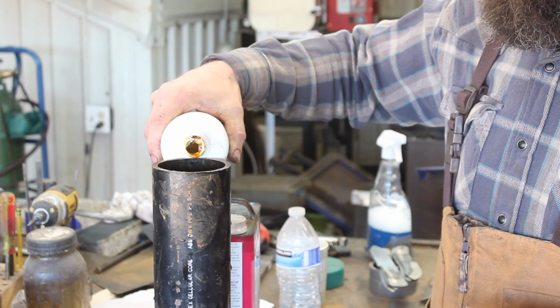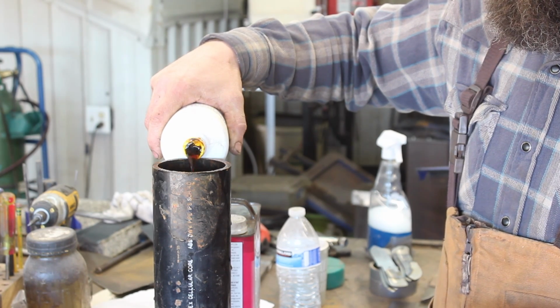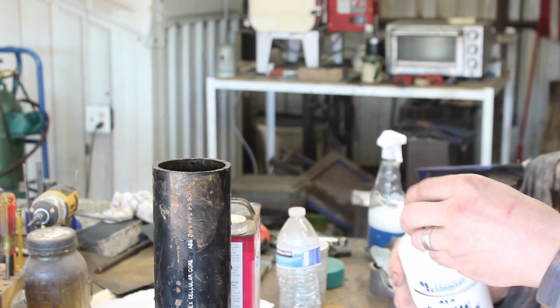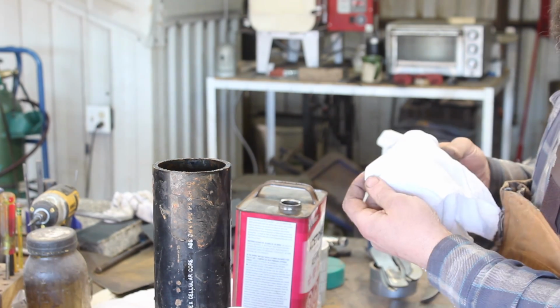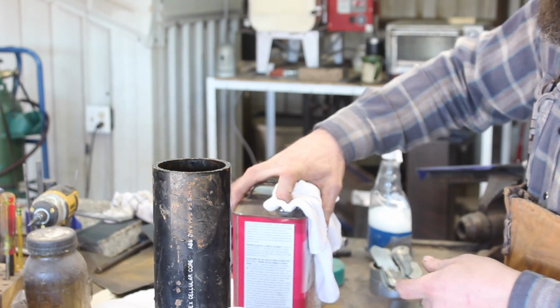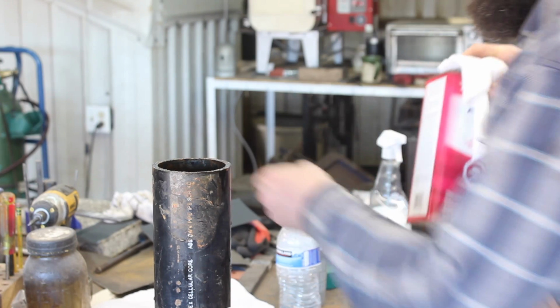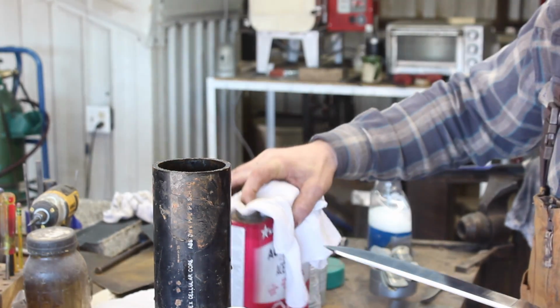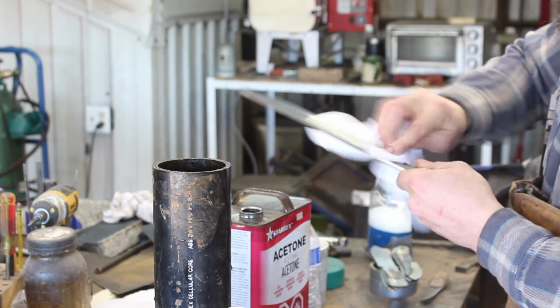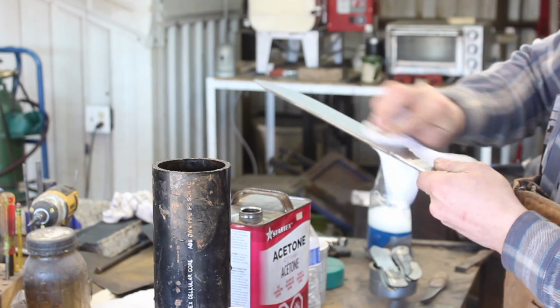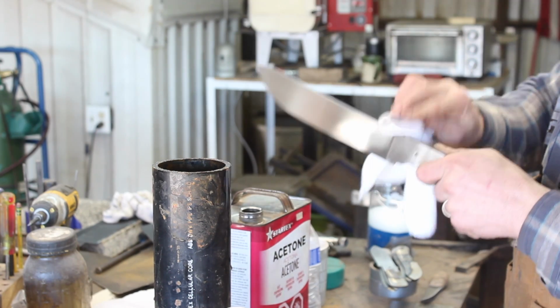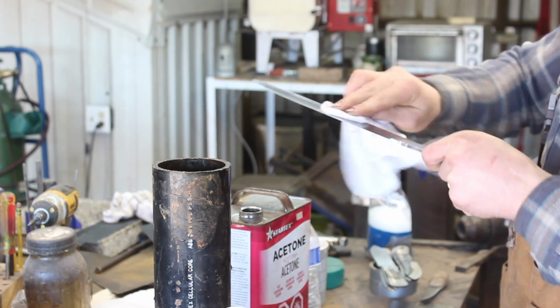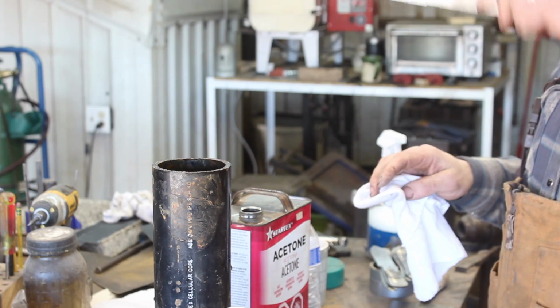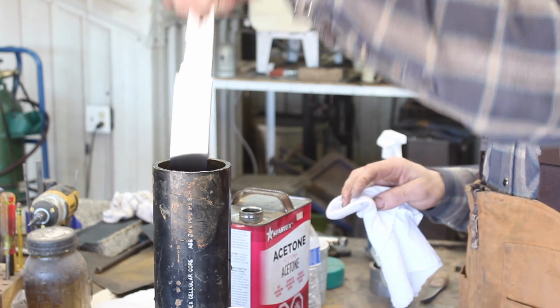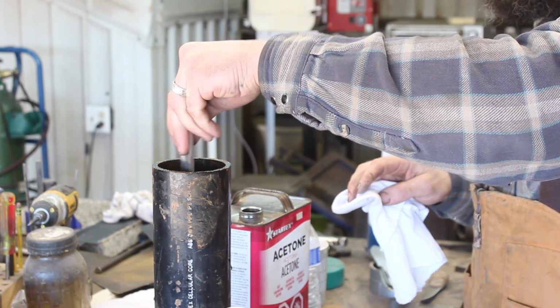So now that I have this blade hand sanded up to 800 grit, I'm ready to go ahead and etch this blade finally. This is great because I'm excited to see what the pattern looks like, and at this point there's been a lot of work gone into this blade, so it's good to reach this milestone here. So like I said, 800 grit, clean it off with acetone, and into the ferric chloride it goes.